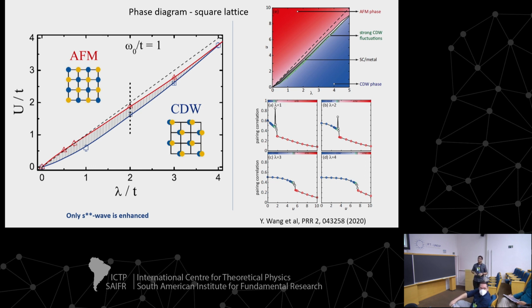I don't know the symmetry, but I would say that the superconductivity here is unconventional because of the effects of the Hubbard interaction. Even in my case, which is S-wave, it cannot be conventional just from the phonons, because the symmetry is not local on site. The pairing is not on site because the Hubbard interaction inhibits the creation of pairs very close to each other. So you have to put them a little bit farther away. I cannot find the gap. Yes, probably they can find the gap. I cannot, I don't have access.